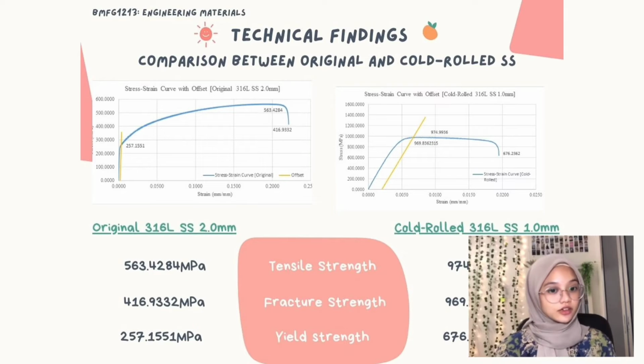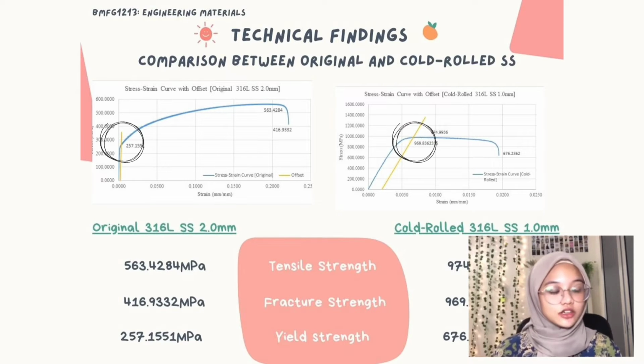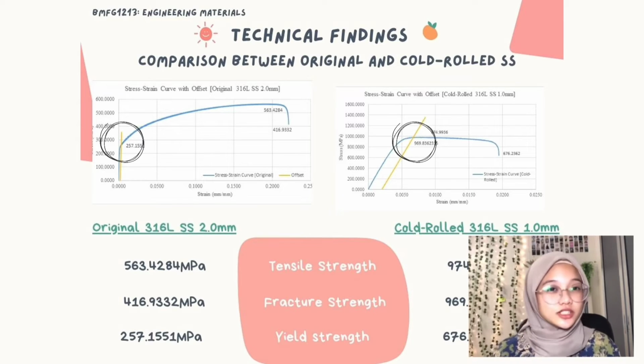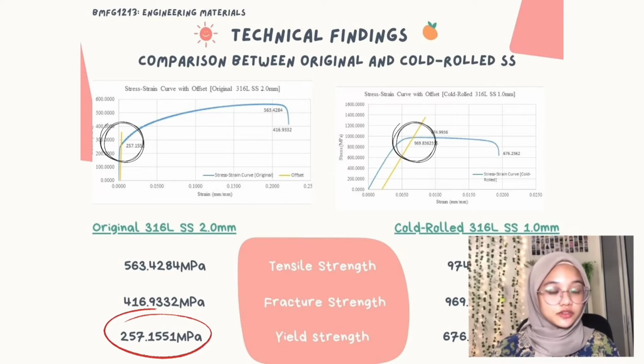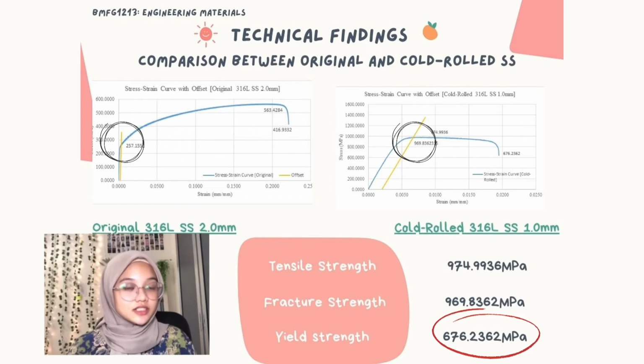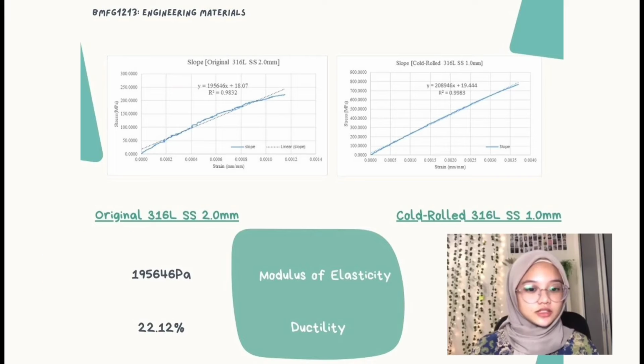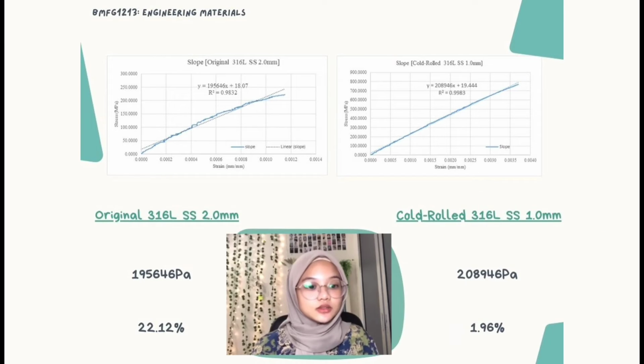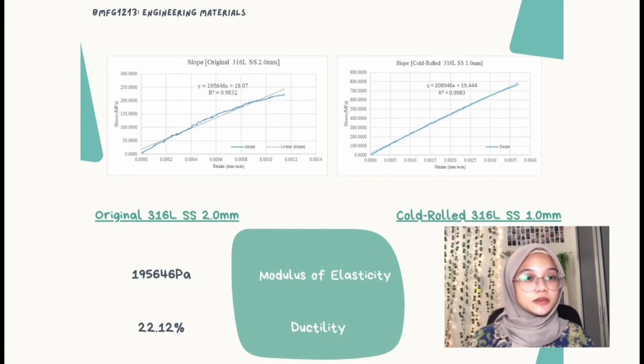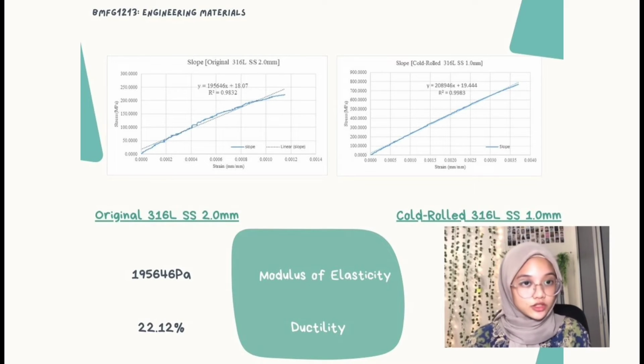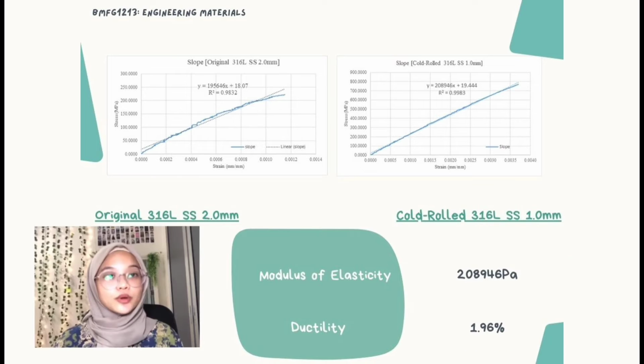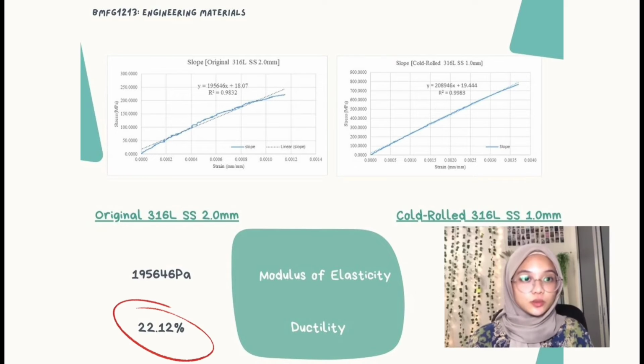Yield strength, however, is obtained from the intersection of the curve with the line parallel to the initial slope of the curve at 0.2%, where we have obtained the values of 257 megapascal and 676 megapascal. These are the graphs that show the slope, also known as the modulus of elasticity, obtaining values as in the slide. The cold rolled specimen, however, seems to have a lower ductility percentage than the original specimen, which is 1.96% against 22.12%.